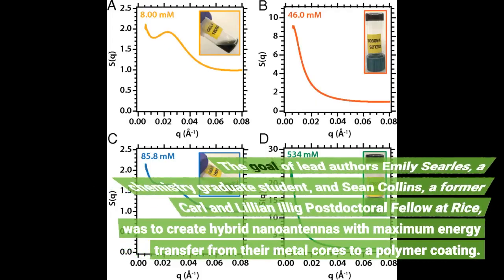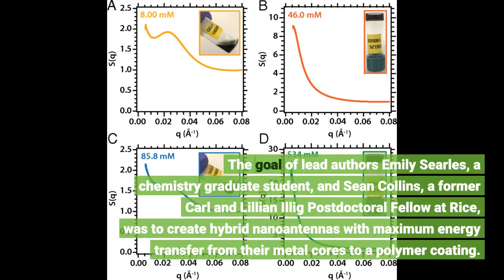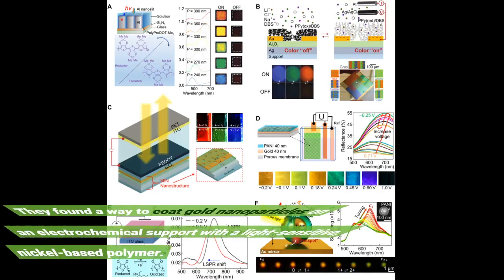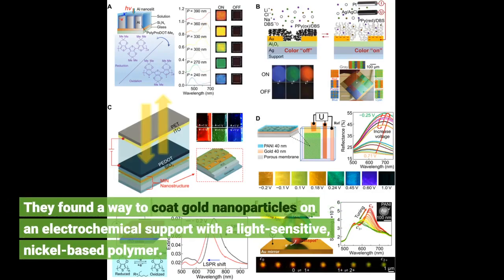The goal of lead authors Emily Searles, a chemistry graduate student, and Sean Collins, a former Carl and Lillian Illig postdoctoral fellow at Rice, was to create hybrid nanoantennas with maximum energy transfer from their metal cores to a polymer coating. They found a way to coat gold nanoparticles on an electrochemical support with a light-sensitive, nickel-based polymer.